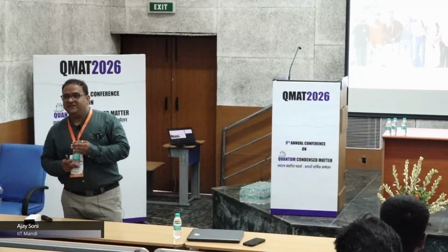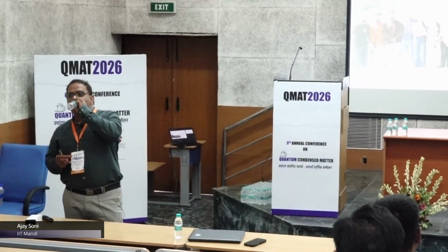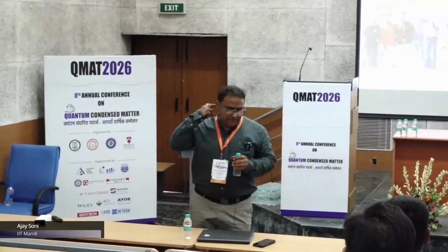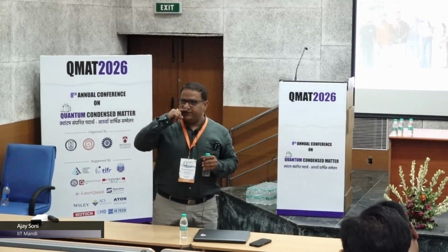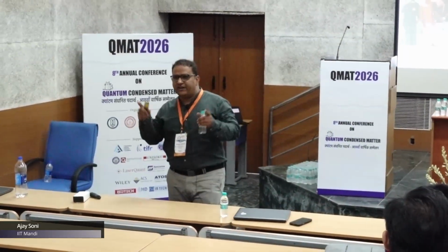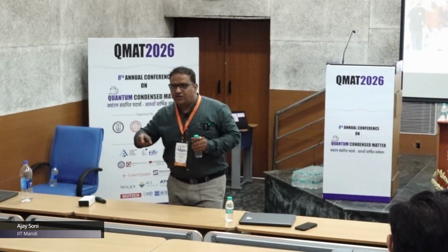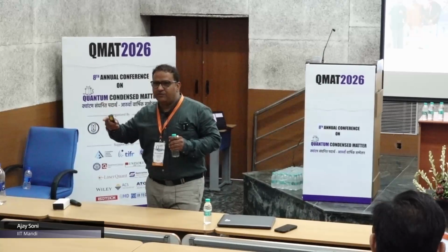Okay, sir. I have another question. You just said that electron phonon coupling strength is known by Fano resonance. Yes. Like how? Okay. Normally, when you have a Raman peak, you fit it with the Lorentzian function. But when you fit it, you don't get the right fitting. So you need to adopt new models. And one of the models is the BWF model, where the Fano is involved.